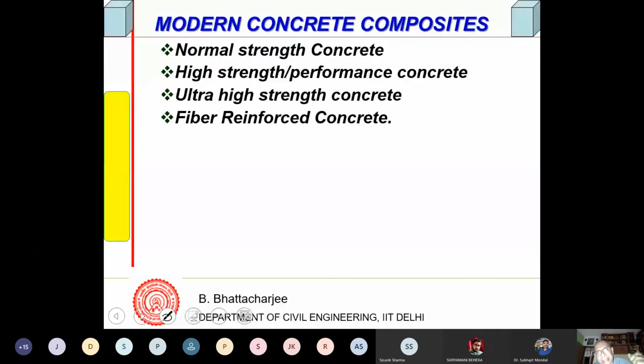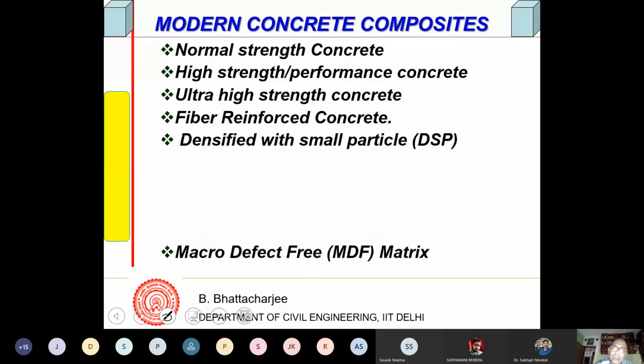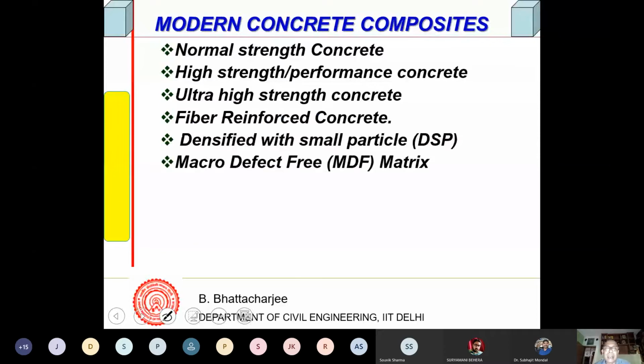Fibers were put in, that has been done quite often because that's a tradition even with mud. So for crack arrestation property, what we call also pseudo ductility. So you see the concrete system is not simply concrete today. There are other very strong materials, like densified with small particles. I'm not going to discuss them. Macro defect free matrix, reactive powder concrete, which can go up to 800 MPa strength. 200 grade is what has been used in structures, also bridges,